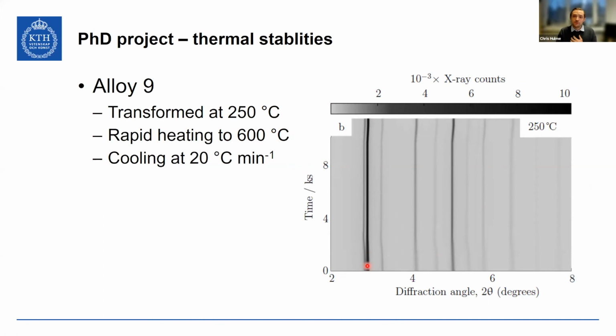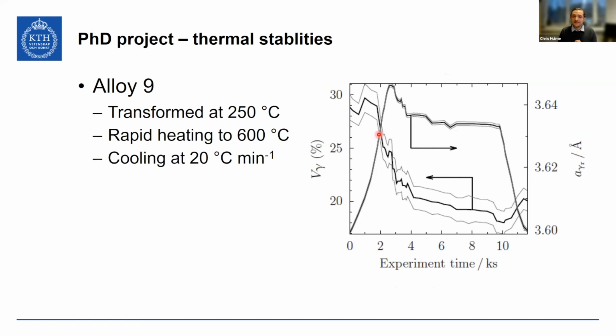And what we can see here is that the austenite actually persists all the way through heating, through holding for about 2 hours after it's been heated. So, you know, 6,000-7,000 seconds, that's getting on for 2 hours. And then quenching back down to room temperature at 20 degrees per minute, still the austenite survives, a lot of it does. And if we look at the lattice parameter and the volume fraction, what we find is that the volume fraction of austenite does decrease, but it stabilizes again at temperature at 600 degrees. And of course, if you did this at 500 degrees, probably it would stabilize at a slightly lower level.